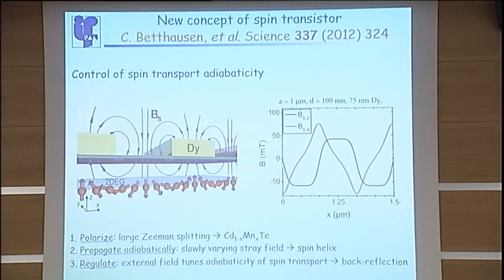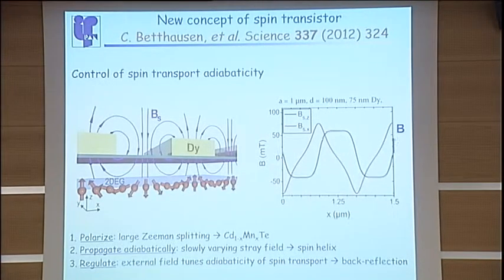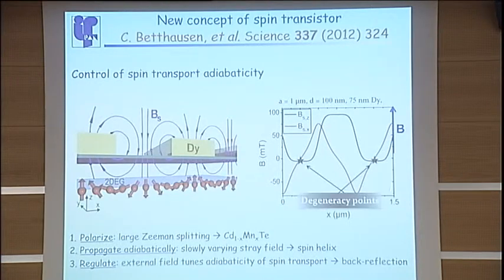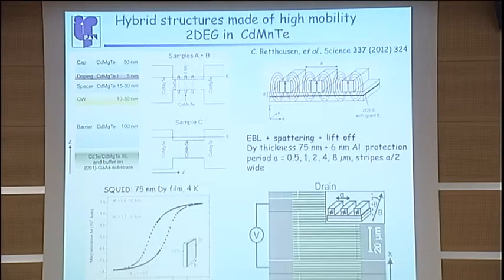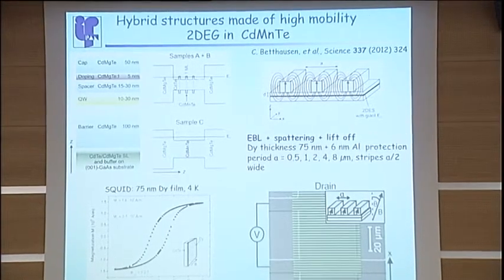Here are the results of a micromagnetic simulation, and you can see the Z and X components. If you apply an external magnetic field so that the magnetic field in the center is compensated, you are left only with the X component, which suddenly, at this moment, changes sign. So you can regulate the adiabaticity and produce back reflection by applying an external magnetic field.